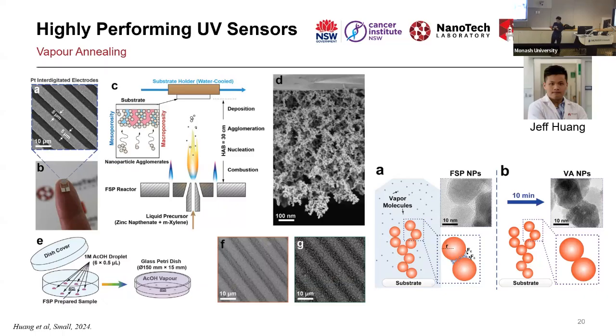If you are dealing with a 1 centimeter square, every time is the same. But the reason we actually wanted to do vapor is, again, scalability. The scalability for vapor is very possible. Imagine that you have meters of coating, and they go into the chamber with all the vapor, and they just get out of the chamber. They can be on a roll, go in there for 10 minutes, 5 minutes, and then get out of the chamber, evaporate, and done.